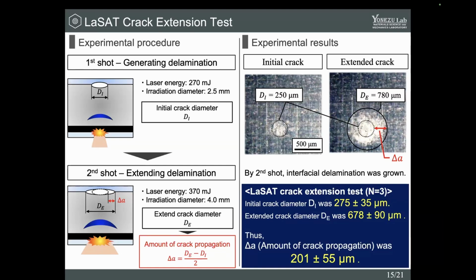And then we continue to irradiate with bigger laser energy and bigger irradiation diameter. And we measured the extended crack diameter, DE. And using DI and DE, we calculated the amount of crack propagation, delta A. This is an experimental result due to two shots. We observed delamination was clearly extended.